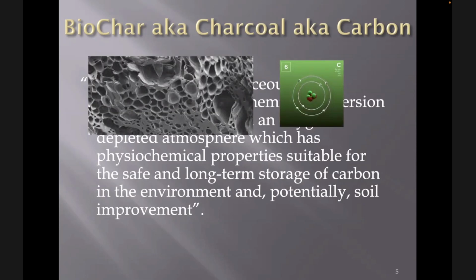So typically it's a fixed carbon. But again, biochar is generated at lower temperatures than, for example, activated carbon is generated at. And so because of that, we also get a combination of other elements present, such as oxygen groups, maybe nitrogen if it's coming from an aquaculture source. But you may also have some volatiles and water present as well, because we're not heating to super high temperatures.